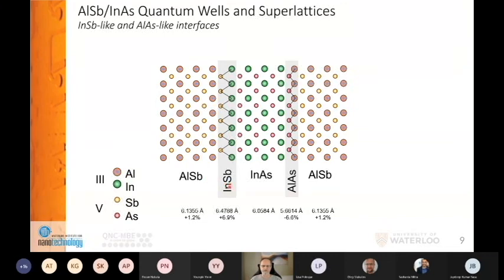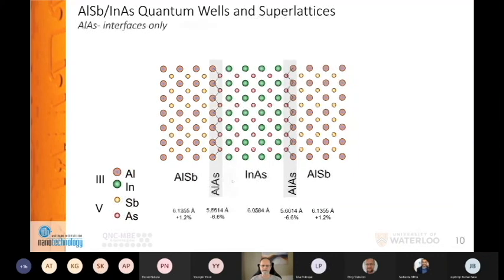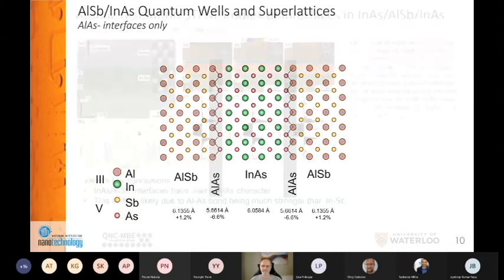The bonds of the interfaces are going to be either indium antimonide-like or aluminum arsenide-like. You can grow different ways, and you can have those interfaces whichever way you like, and you can have mixed interfaces which effectively are not going to be that strained, but the strain is considerable, about 6-7%. So those are either tensile or compressively strained interfaces. And this is just the beginning of the issues with this material system when it comes to controlling the interfaces.